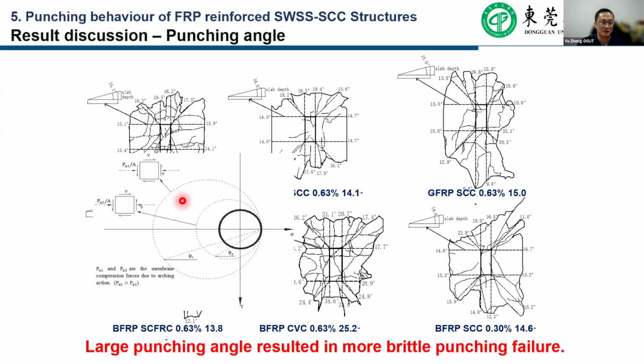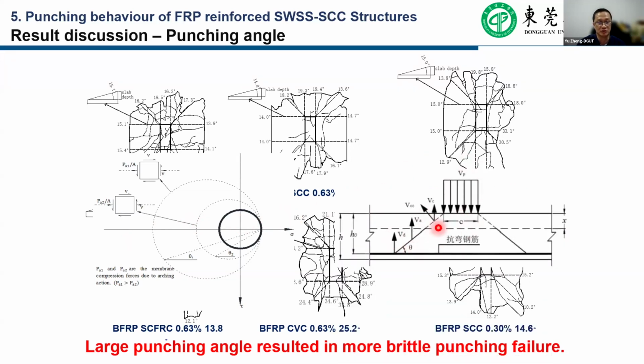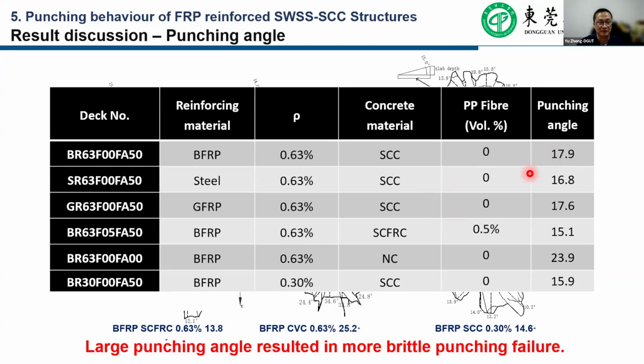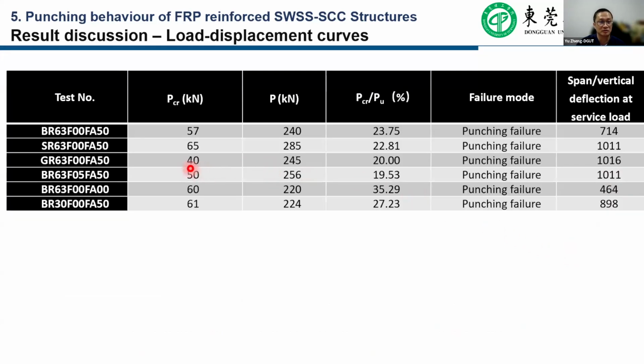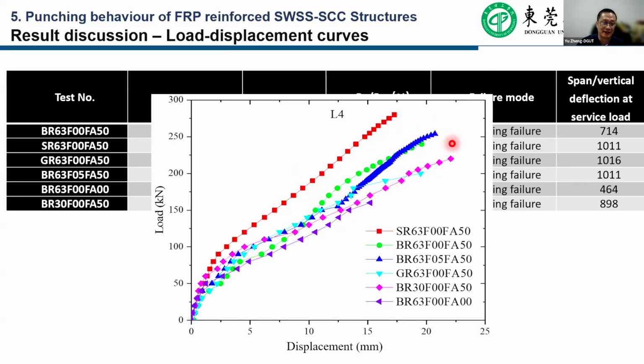Using this method, we find that if we increase the horizontal restraint, the punching angle could be reduced. That means a higher punching capacity can be obtained. We also use that to predict it, and find that in this method, the restraint stiffness is fixed, so the punching angle is also fixed. We also studied the cracking behavior with the ultimate strength, and it is expected that bilinear behavior can be found for those deck specimens.